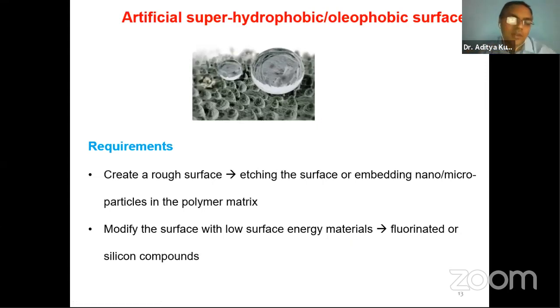And how do you create the low surface energy material? What does a low surface energy material mean? It means they have some alkyl chain, a long carbon chain, like polymer, silanes, or fatty acids. So these have a polar component and a non-polar component. The polar part has one functional group which will attach to the surface, and the non-polar part will go upward. So these are hydrophobic tails. And this non-polar part will repel the polar component of the water, because water is polar. So non-polar, polar repulsion gives you the super-hydrophobicity.